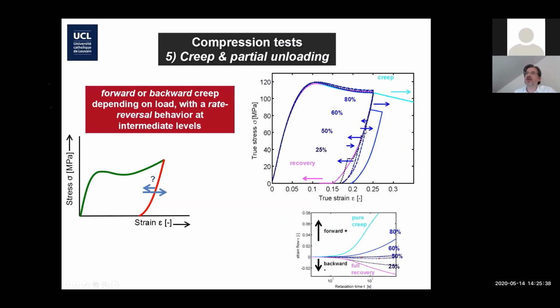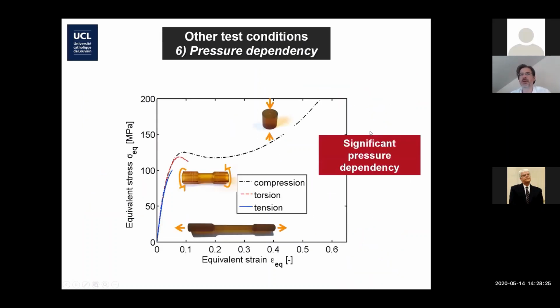And basically with, I think, all phenomenological constitutive models that are available, you will not be able to predict this. By the way, this is something that has been observed on nanocrystalline metals, and the origin is related to very significant back stresses. So you got the message here about this creep recovery and this non-stagnation point in this rate reversal effect that we found here.